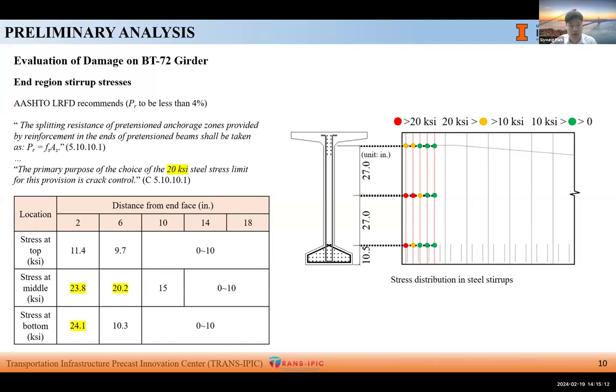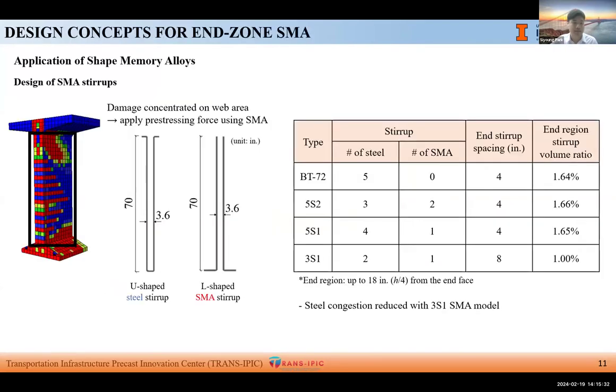However, after that, the stress diminished quickly, and after third stirrup, the stress reached below 10 KSI. We can see that most stresses are distributed within third layer, implying that these regions are really vulnerable to cracks. As a result, SMAs were replaced within third layer in further analysis.